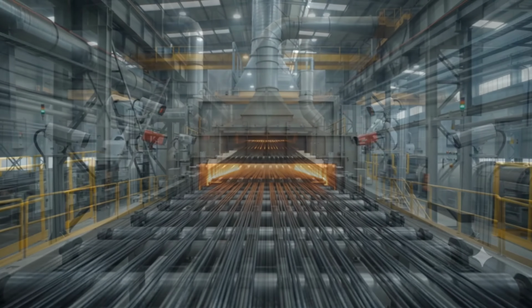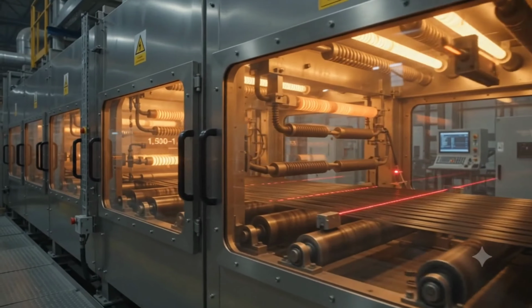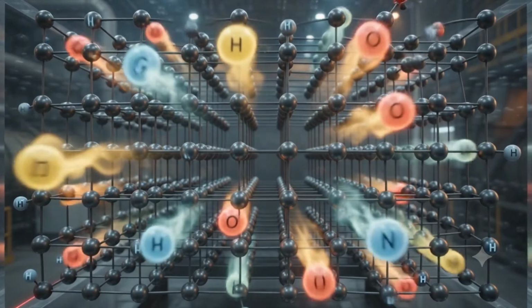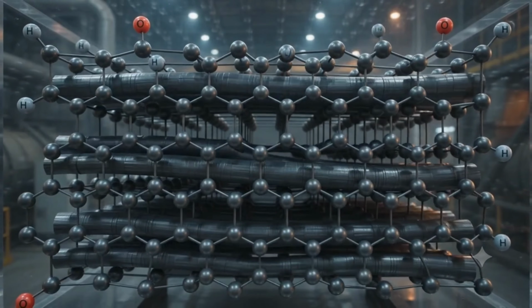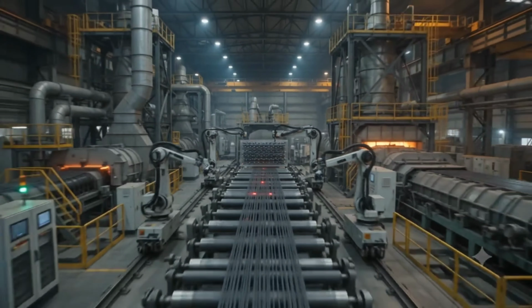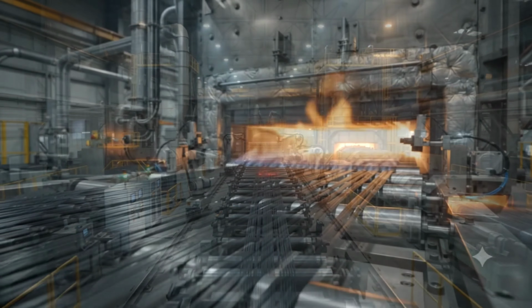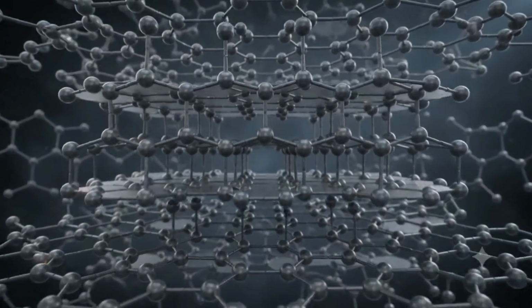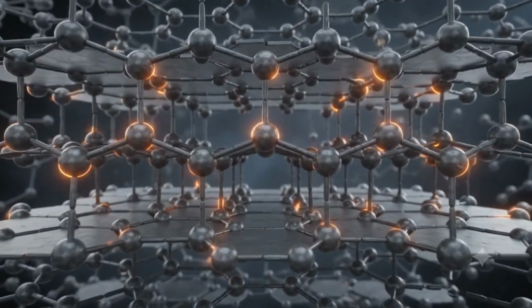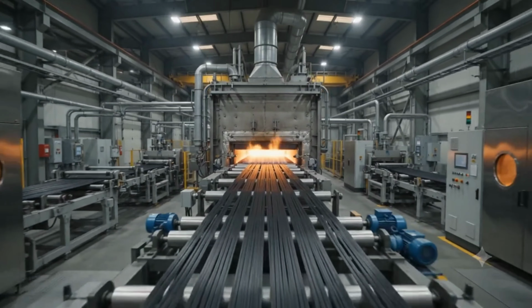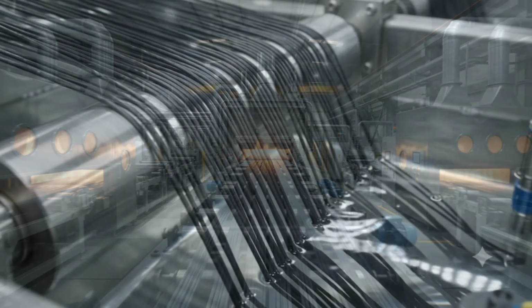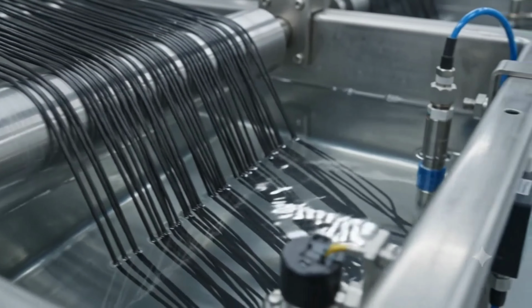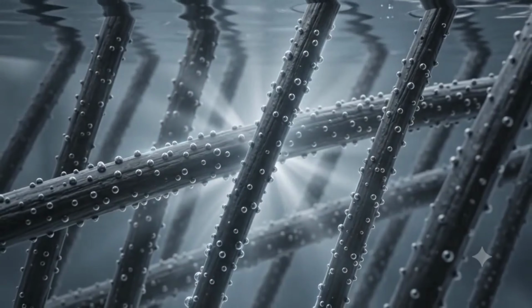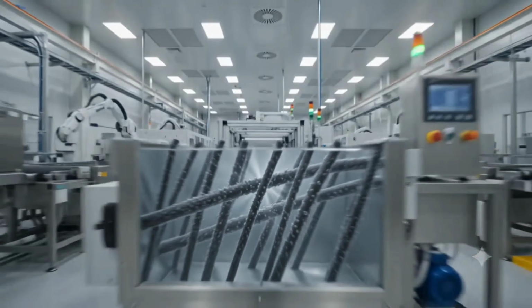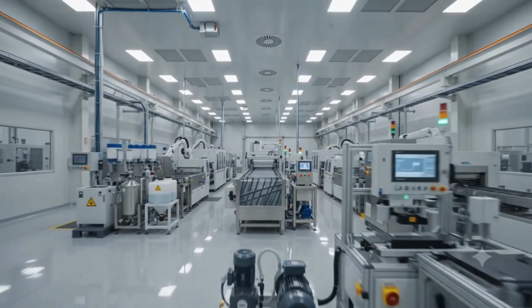At nearly 1800 degrees, the fibers become almost pure carbon, gaining the remarkable strength and durability that define this extraordinary material. At temperatures approaching 3000 degrees, carbon atoms align into perfect crystal structures, unlocking the extraordinary strength that makes carbon fiber exceptional. Electrochemical treatment creates billions of microscopic bonding sites, allowing carbon fibers to permanently unite with advanced composite resins.